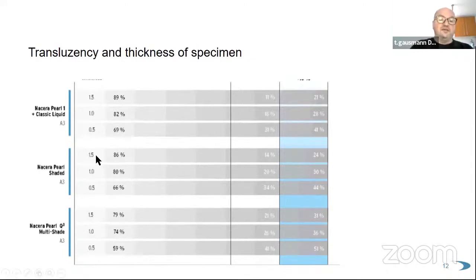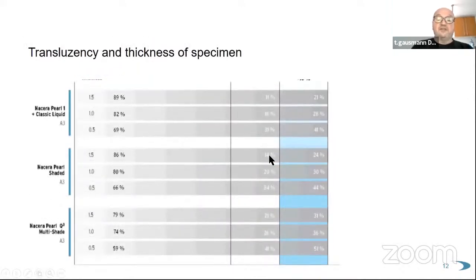So you can see here, a specimen thickness of 1.5 millimeter is giving you 86% of opacity, so for sure 14% of translucency in A3. But then marketing comes in and says, can't we take the raw material and measure the raw material, because it looks better? So we take the raw material without any color, which is not correct, but you can do it. Measure the raw material, you get 10% more. You get 24% translucency, looking much better. Going down, specimen thickness 1 millimeter, you get 30% already. Going down further, at a specimen thickness of 0.5 of a millimeter, you get a fantastic 44% translucency.